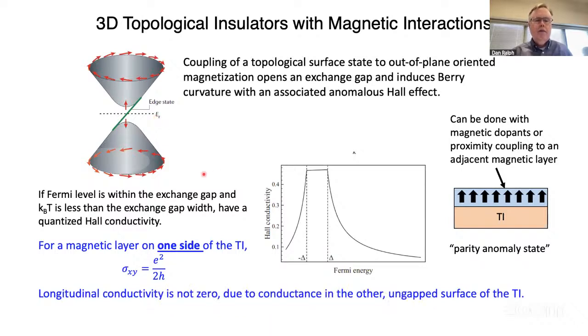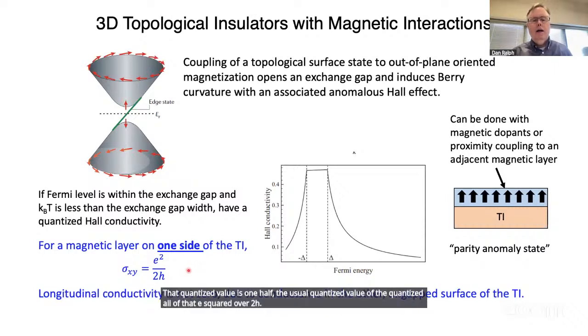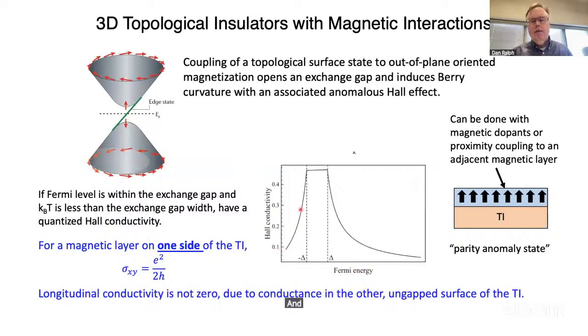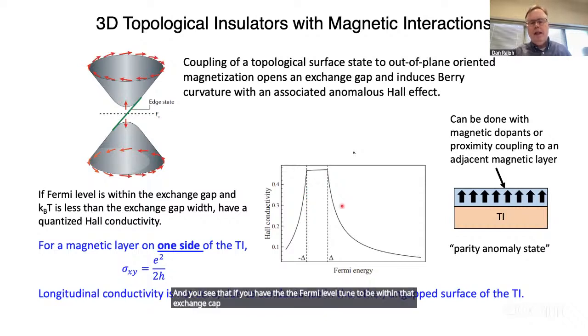If you just have a topological insulator flake with a magnet on one side, that quantized value is 1/2 the usual quantized value of the quantized Hall effect, e²/2h. And you see that if you have the Fermi level tuned to be within that exchange gap. So that's shown here schematically within this diagram.